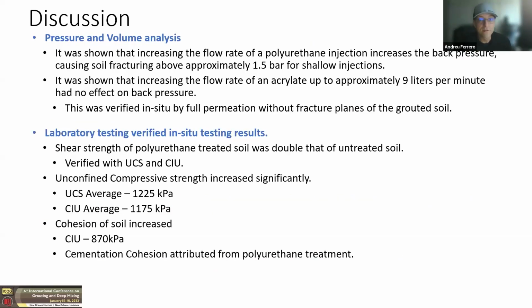It was shown that increasing the flow rate of the polyurethane injection increases the back pressure, causing soil fracture above approximately 1.5 bar for shallow injections. And then quite the opposite with the acrylate, increasing the flow rate had no effect on back pressure. And we theorize that that's because the viscosity of the acrylate is just so low that it wasn't creating any kind of pressure resistance within the soil itself.